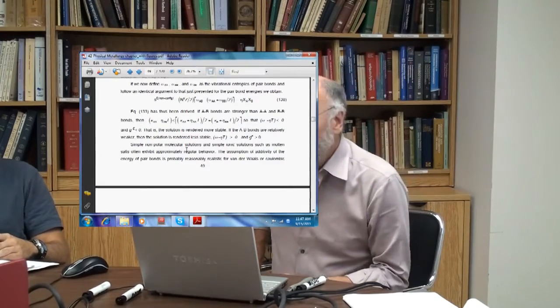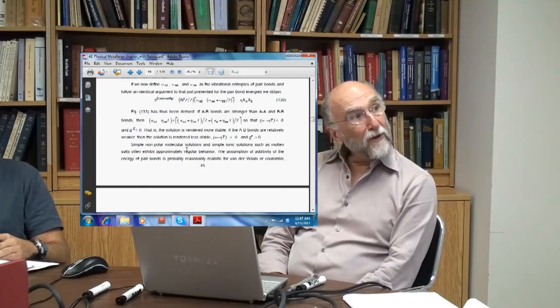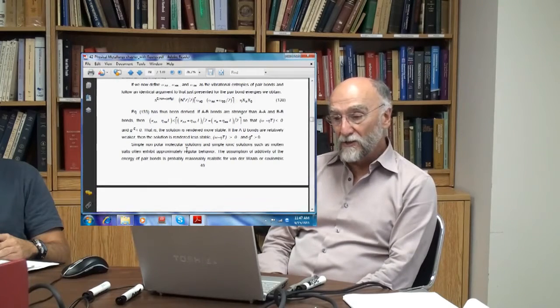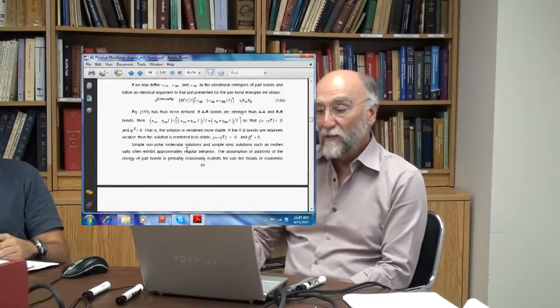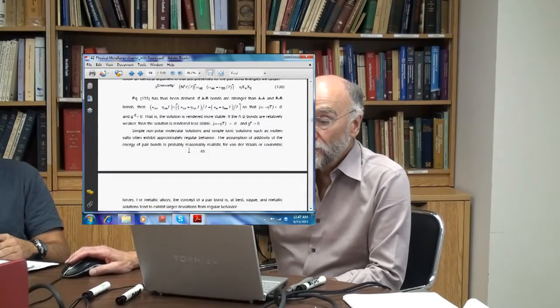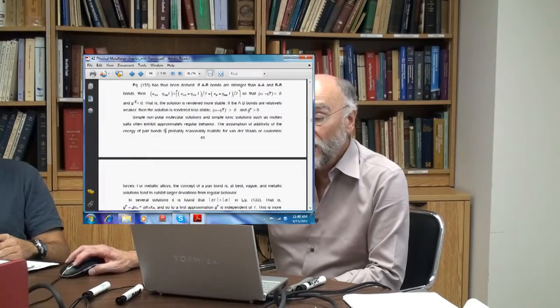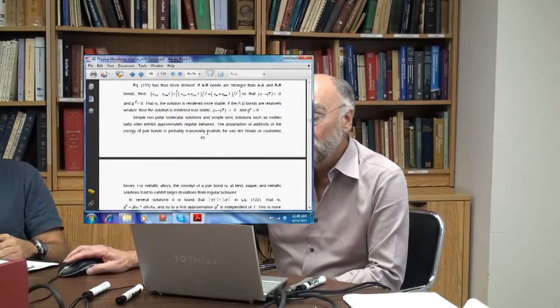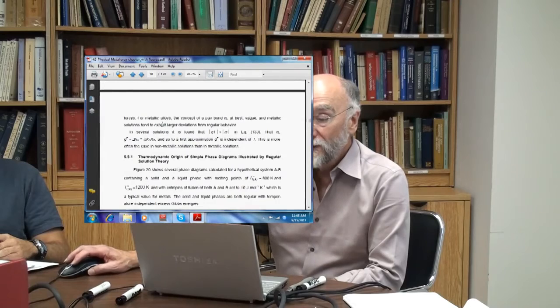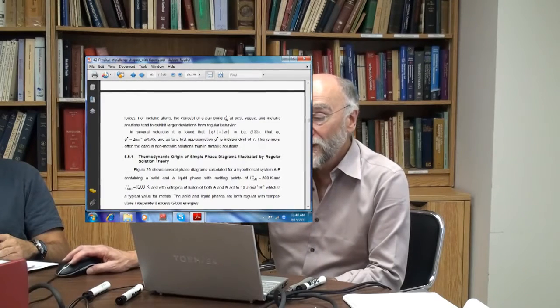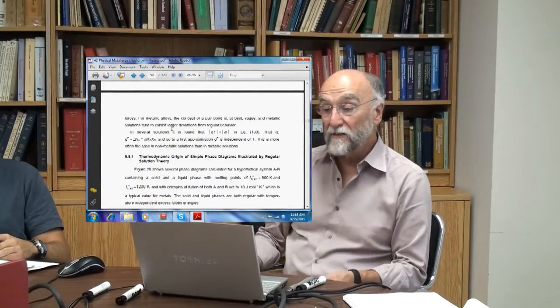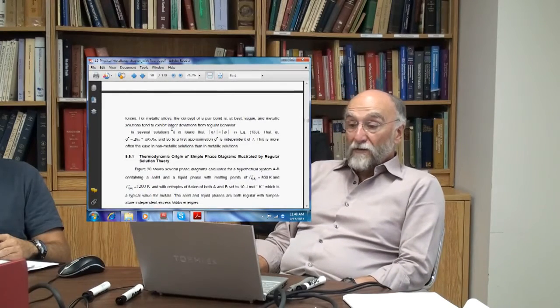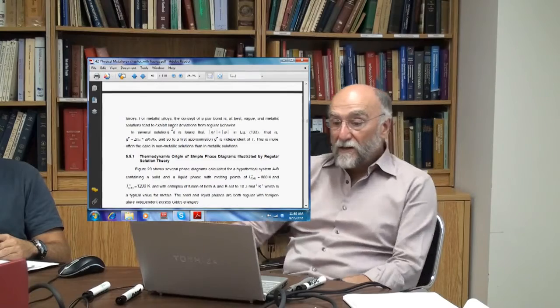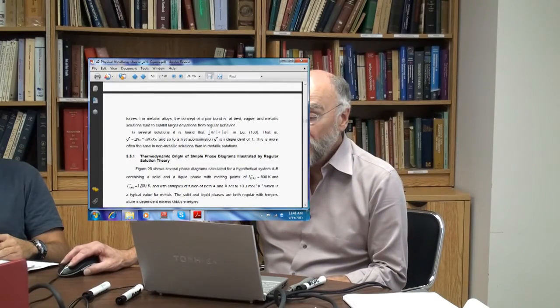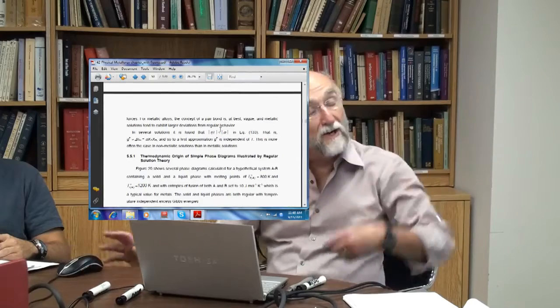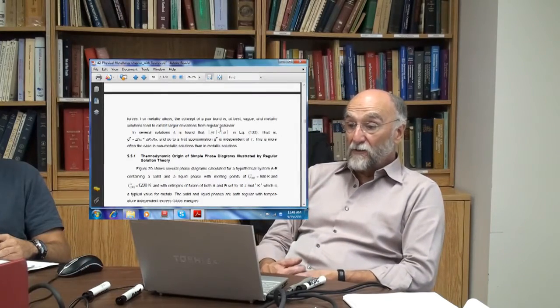And I think you kind of observe that. You find the regular equation seems to apply more closely to solutions such as ionic salts and simple molecular solutions than it does to metals. So the assumption of additivity of the pair bond energies is probably reasonably realistic for van der Waals or Coulombic forces. For metallic alloys, the concept of a pair bond is at best vague, and metallic solutions tend to exhibit larger deviations from regular behavior, both in the heat and even more so in the entropy. I said here, in several solutions it's found that T·S^XS is much less than omega, so the excess entropy term is generally less than the enthalpy term.